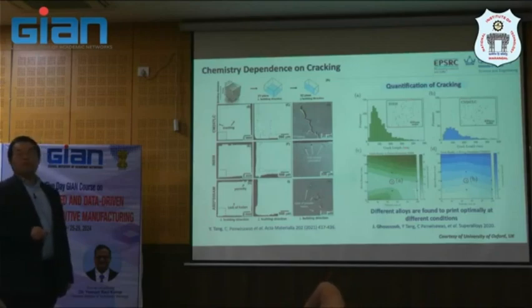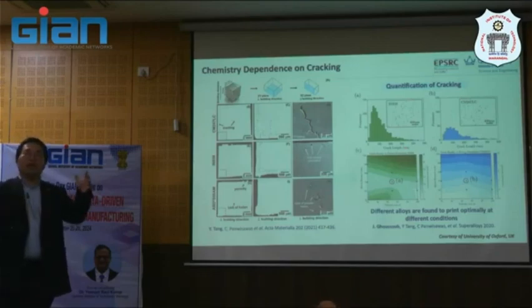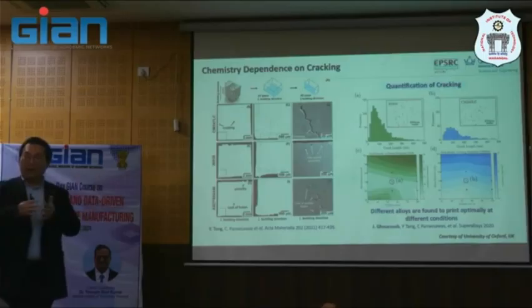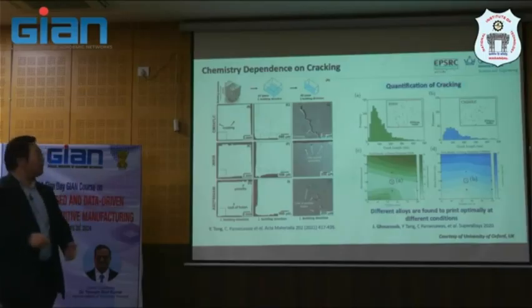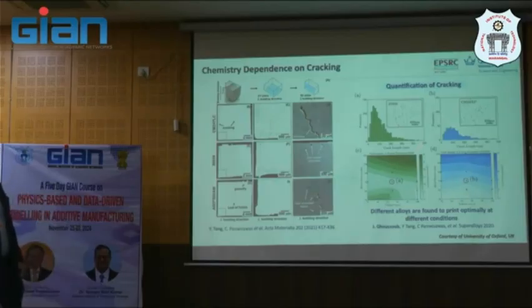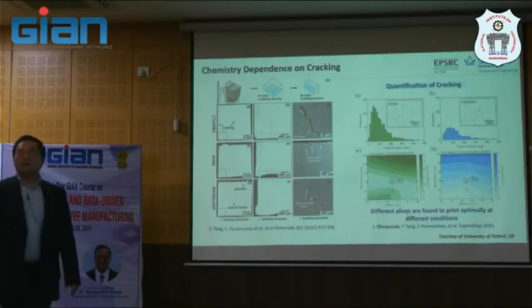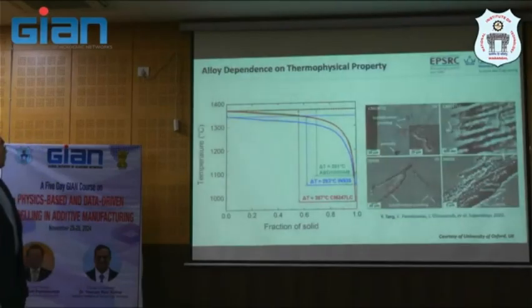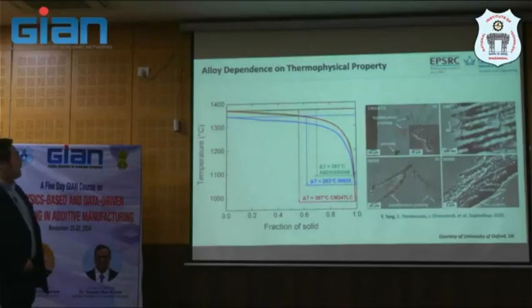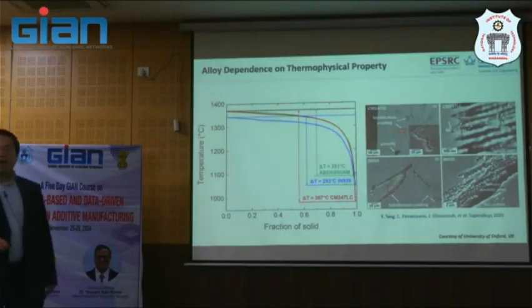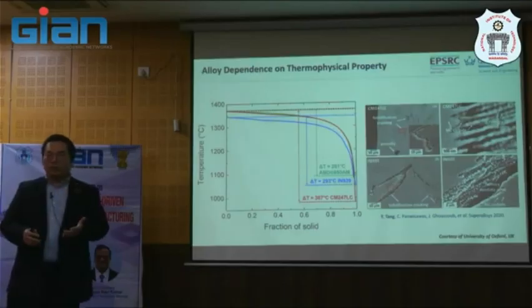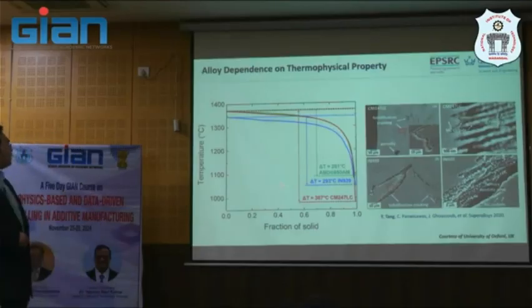So we quantify this for the whole 2D section. At least it's not 3D yet, but it's several sections along the build direction that you can get some statistics from. Again, this is not an easy job; you need to do a lot of experiments to do serial sectioning. And this is basically related to the alloy-dependent crack, that we use a non-equilibrium Scheil model to